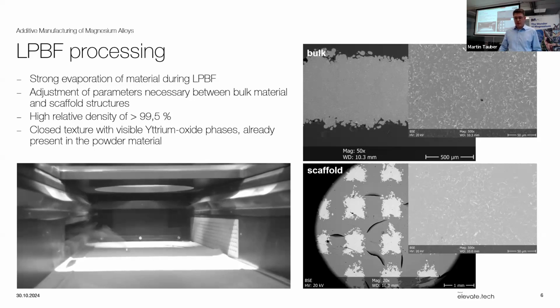And as you can see, like I mentioned, we need quite a lot of energy to crack the surface of the material to melt it, because it has a ceramic surface because it was oxidized. We need to crack this to melt it, but then we have a lot of energy which also partly vaporizes the material, leading to this kind of smoke you can see there. And we adjust the parameters between bulk material and also scaffold material, which is the more interesting part for us in the medical sector.